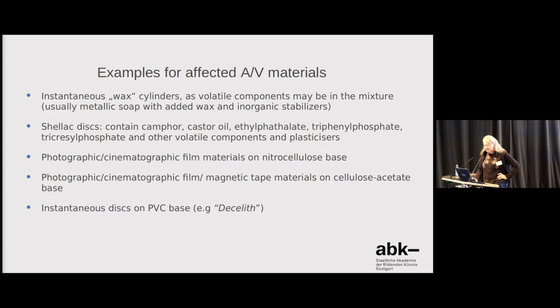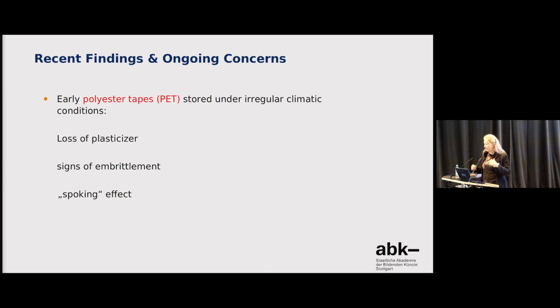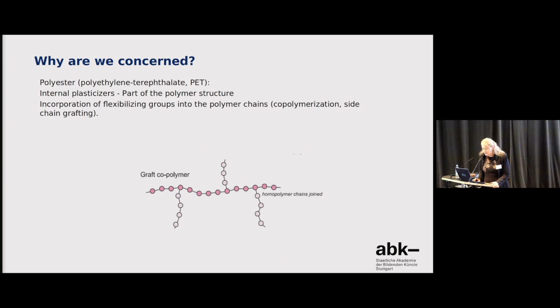So, examples for affected materials, we all know them, from instantaneous or wax cylinders to shellac discs to photographic, cinematographic film materials on nitrocellulose as well as on cellulose acetate, instantaneous discs, and so on. But recently, in one of my archive destinations, I found early polyester tapes stored under irregular climatic conditions, which showed signs of loss of plasticizer, embrittlement, and spoking effect. And this is something which concerns me, because PET usually does not have a mixture of plasticizer, but is internally plasticized, which means that the plasticizer is a part of the polymer structure.